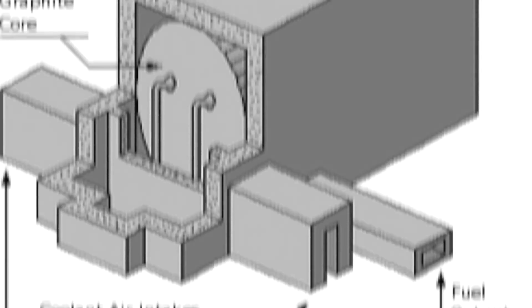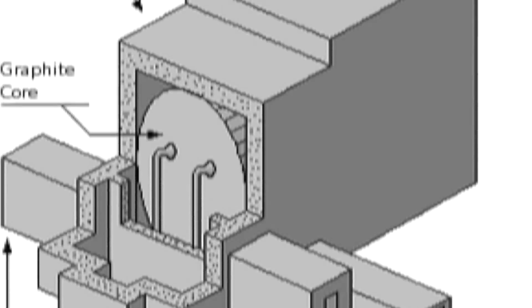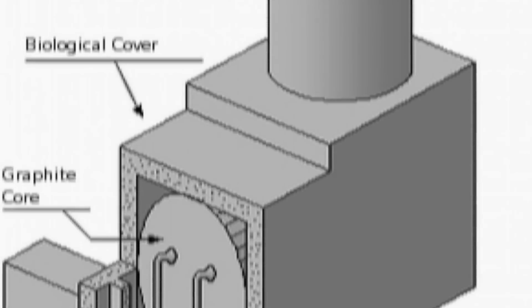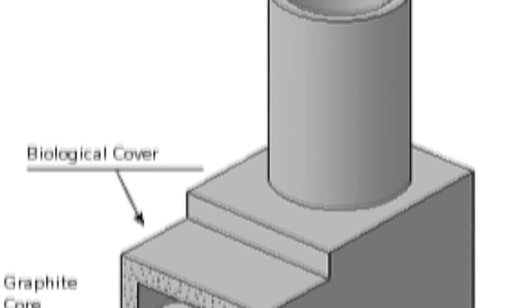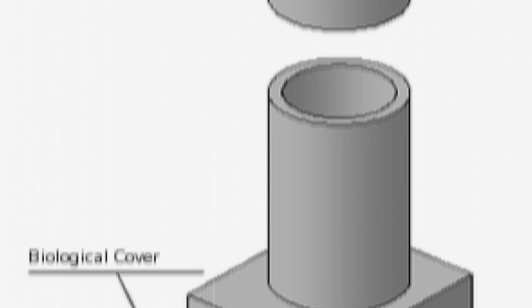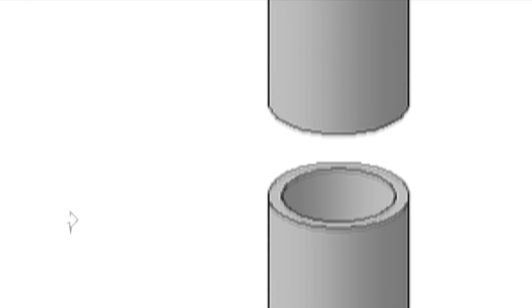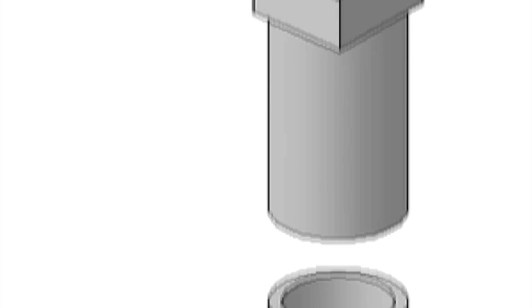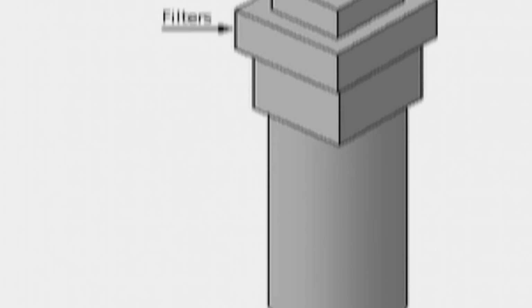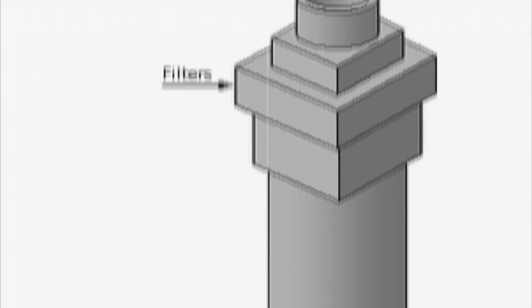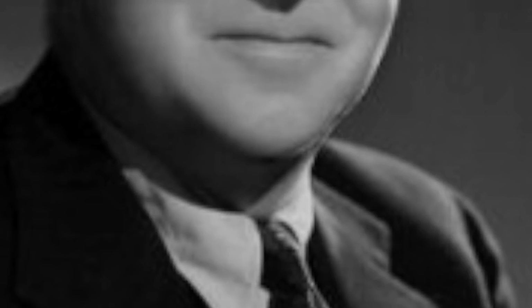This became evident after 2 years of operation, when there was an unexpected temperature rise in the core. In one case, this occurred when the reactor was shut down. To combat the accumulation of Wigner energy, the operators of the Windscale reactor introduced a process in which the stored energy was removed by heating the graphite bricks to temperatures of 250 plus degrees Celsius, a process called annealing.